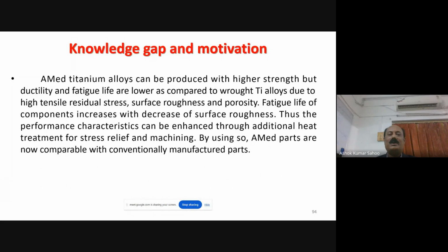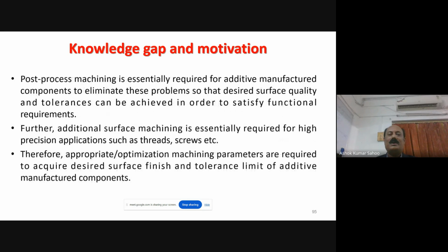Additive manufactured titanium alloys can be produced with higher strength, but the ductility and fatigue strength are lower compared to wrought alloy due to high tensile residual stress, surface roughness, and porosity. Fatigue life also increases with the decrease of surface roughness. Therefore, the performance characteristics can be enhanced through an additional heat treatment process for stress relieving. It has to be carried out. By doing so, additive manufactured parts are now comparable with conventionally manufactured parts.